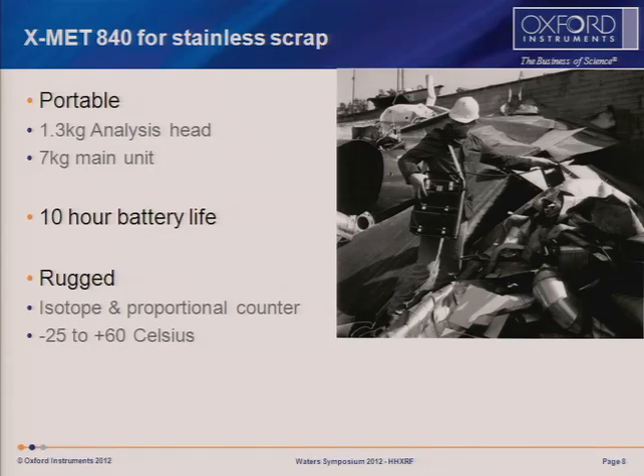And here's the electronics box. It's pretty heavy, but you can manage it. You have to manage it for 10 hours because it's got quite a sizable battery in there as well. Incredibly robust. A company that's based in Finland knows you've got to be able to work with it outside at minus 25. And if you're in the hot end of the steelworks, you need it to be working when it's hot as well. So this was incredibly rugged and truly handheld and quantitative.